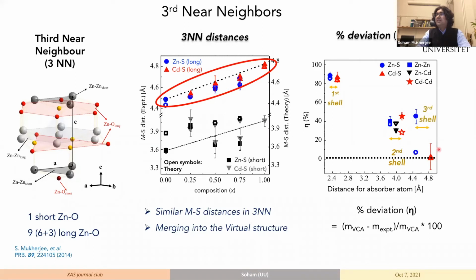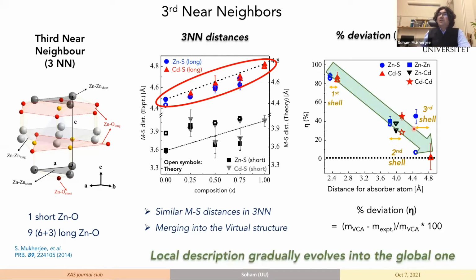And in the third near neighbor, we see that for the cadmium, this actually merges with the zero line, but for the zinc, it still did not. Which means that probably farther ahead, if we still had data until that time, unfortunately we don't, you will see that the local description will completely merge with the diffraction information that you get. So when we go from a distance of 2.4 angstroms to roughly around 5 angstroms from the absorbing atom, you will see that there is a gradual evolution of the local structure into the global structure.